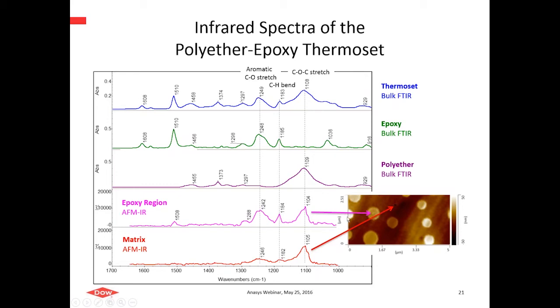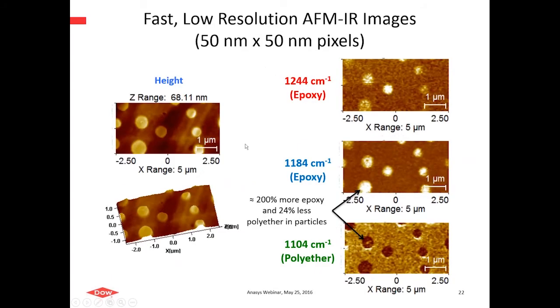So if we look at these rigid domains, in fact we do see more CO stretch and CH bending associated with epoxy in those domains relative to the matrix, which is more polyether-rich based on the local spectra. And then, as before, we can go ahead and start mapping. Here's the field of view on the left, showing you the height and top-down perspective. And then we map a couple of bands associated with the epoxy, and that lights up those small domains in the morphology relative to a band that lights up essentially the matrix polyether.